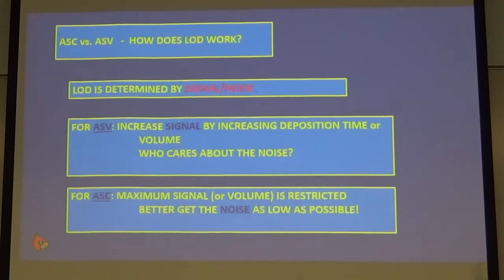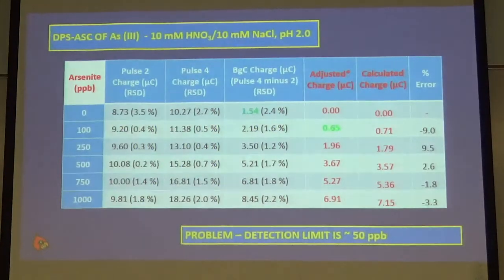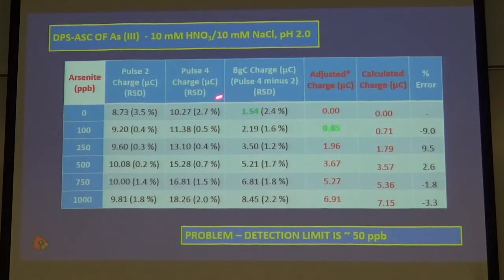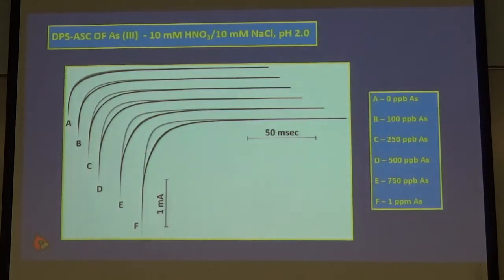Well, again, the problem is that the background that you get is too big. As our signal gets smaller, it's getting closer and closer to that. And when our signal is going to be close to 1.5 microcoulombs, we're not going to be able to measure it very well. So, again, that's that curve A for the 0 arsenic. And if you look closely, you can see it's not 0. That's the 1.5 microcoulombs. We want to diminish that by decreasing the electrode area.